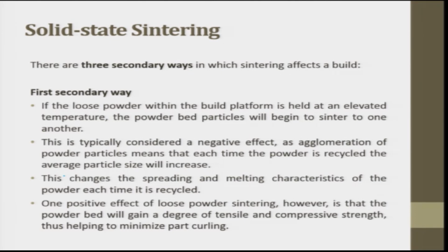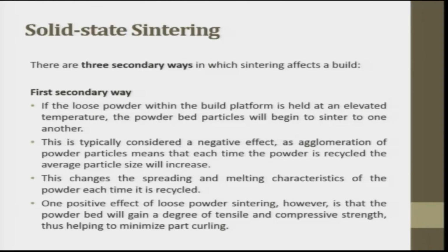So you can't keep it maintained at a very high temperature. After some time, you have to maintain a slightly lower temperature such that it does not sinter. This is typically considered a negative effect, as agglomeration of powder particles means that each time the powder is recycled, the average particle size will increase because it is all getting stuck.